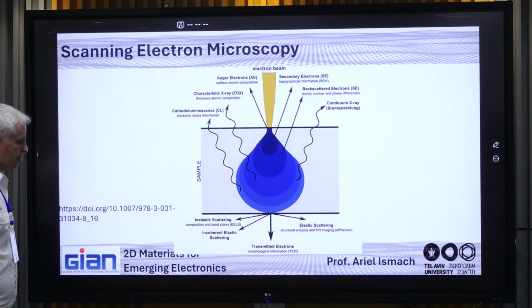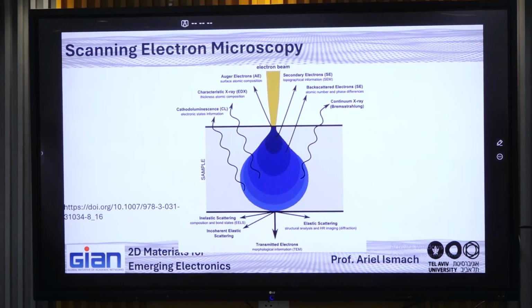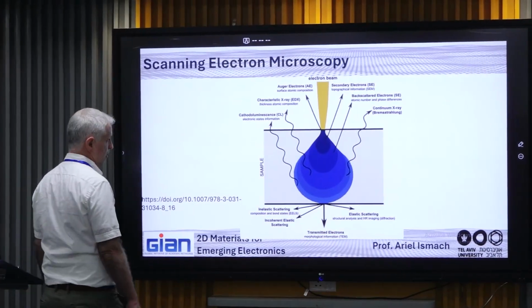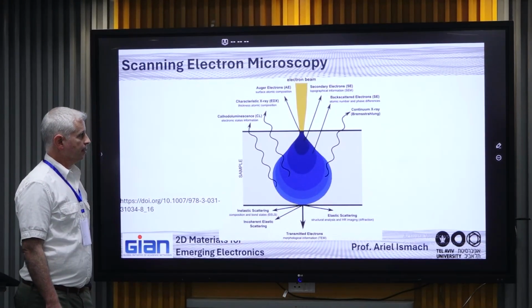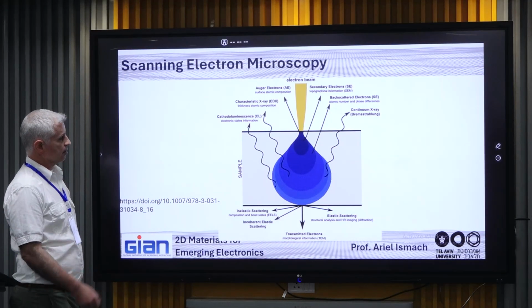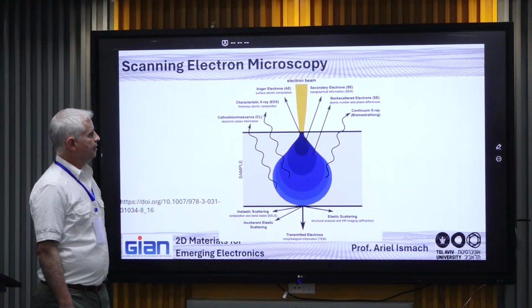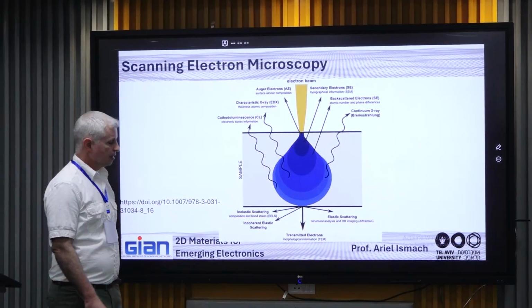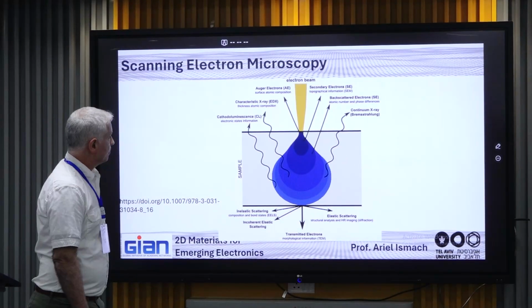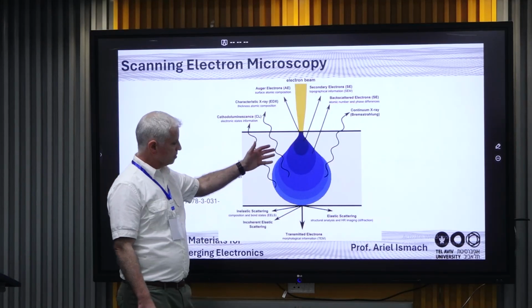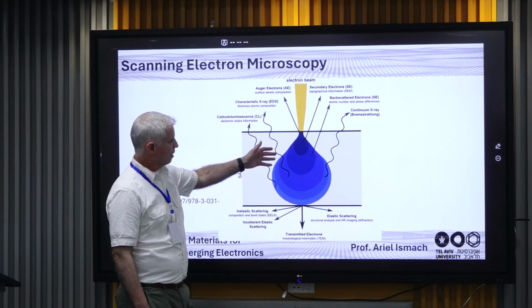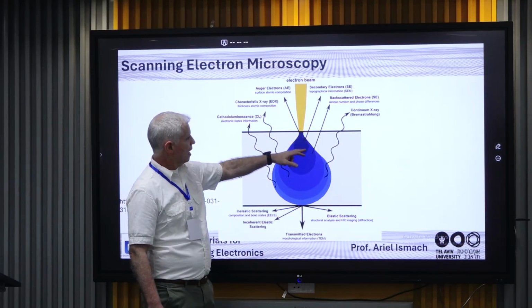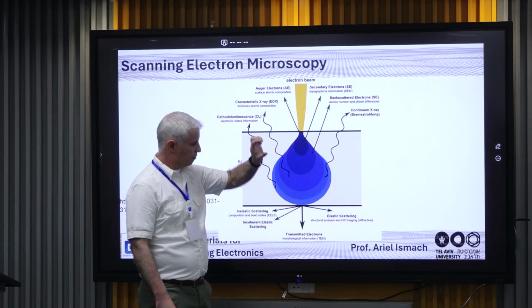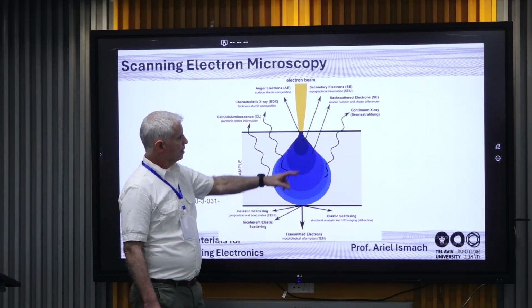When the electron hits the surface, a lot of things can happen. A lot of interactions happen simultaneously. Of course, every interaction has its energy range and its characteristics. So we can, in principle, study any of these interactions in order to extract some information about the material, chemical information, morphology, etc. You can see here the most known interactions are the secondary electrons, which happen only in the few nanometers range in depth, and then deeper than that